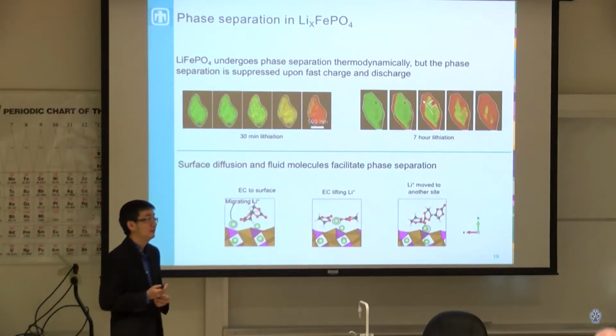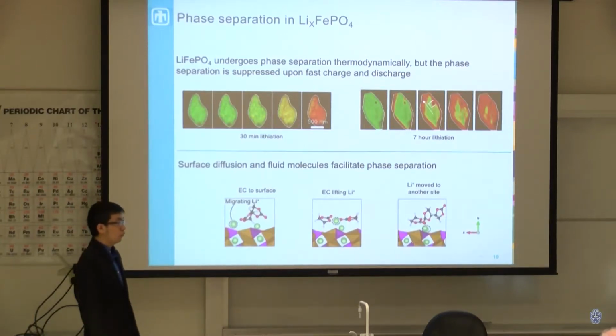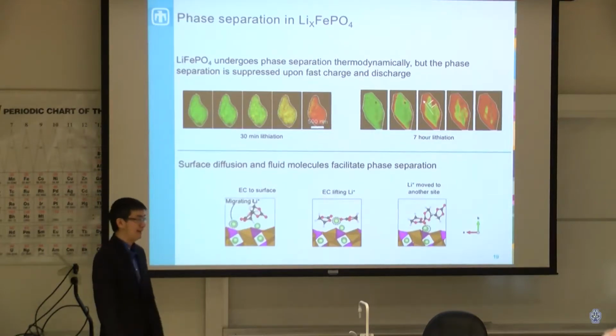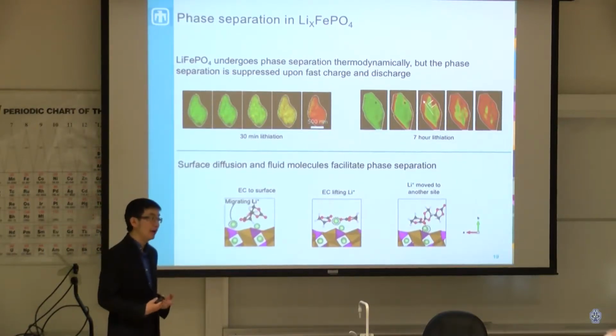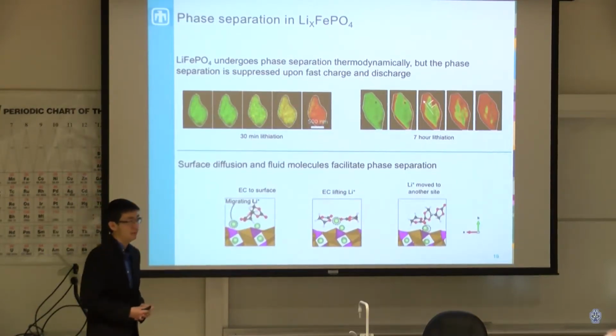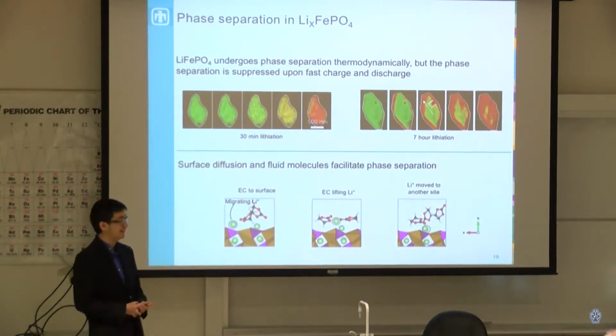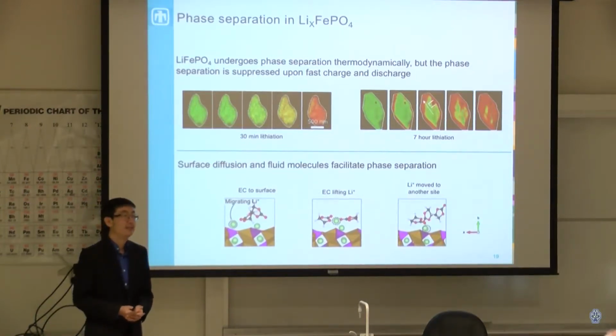You're saying you found that a process that may not currently be done, you need to investigate coating these particles to suppress this motion and migration of lithium, what we're calling phase separation. We're suggesting that this is the mechanism, and coating could be one way of suppressing this mechanism. But we haven't found a coating that works yet. Like a good surface coating, a surfactant coating? Yeah, like a surface coating, surfactant coating. Definitely.